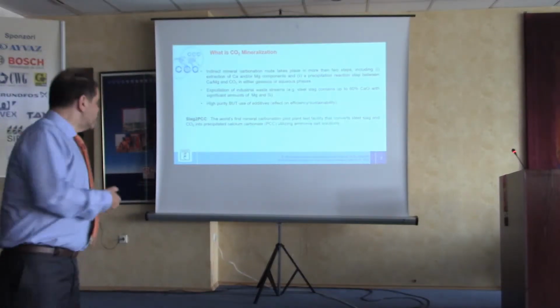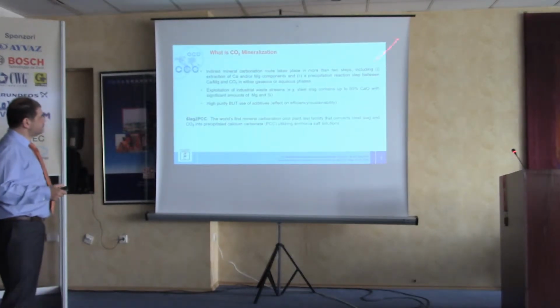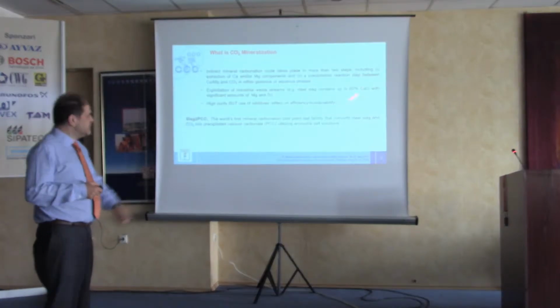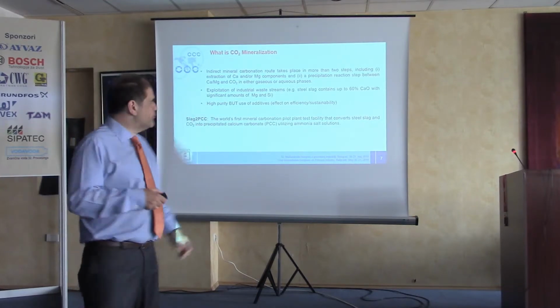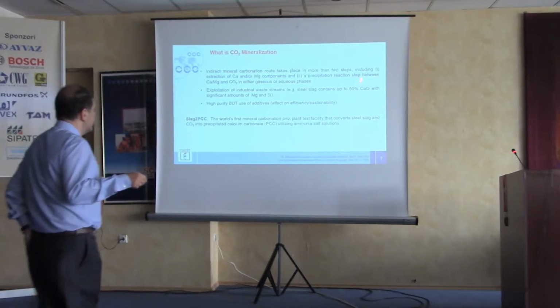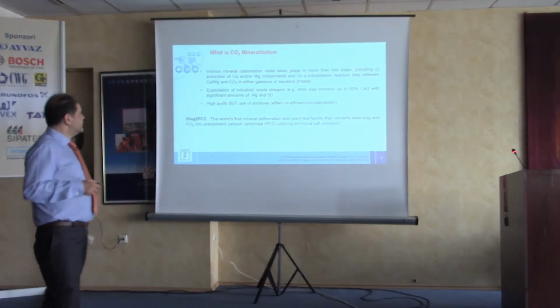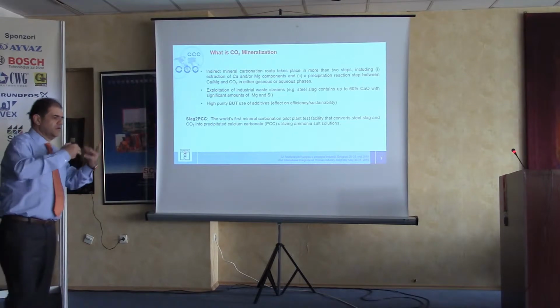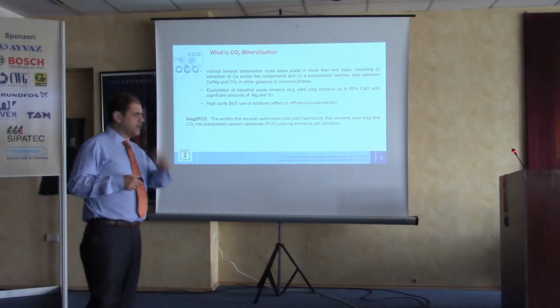So what we want to do is try to use the waste to remove CO2, okay? So this is what we do. We extract components from the waste of the industries. For example, steel slag, I mean all this waste liquid that comes in the steel making process, contains up to 60% calcium oxide, okay? So we found our calcium, and then we do a precipitation reaction step. This is where we come in, this is a part of this research work, and we react, we gas the CO2 with a diluted mixture here, to produce something called calcium carbonate.